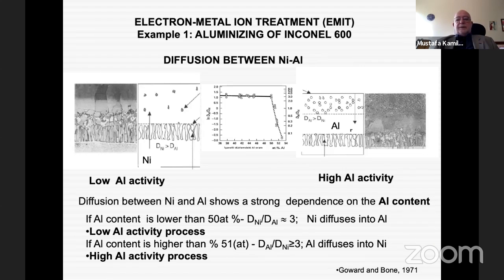When you look at the behavior of diffusion between aluminum and nickel, it shows an interesting behavior. When the aluminum content of the nickel aluminum alloy is lower than 50 atomic percent, nickel diffuses into aluminum, and this is named a low activity process. When nickel diffuses into the aluminum, you end up with this kind of a structure because nickel comes from the substrate material and goes into the aluminum layer. So in between, this layer starts to appear. This is the layer that has been the remnants of chromium compounds that are present in the nickel alloys.